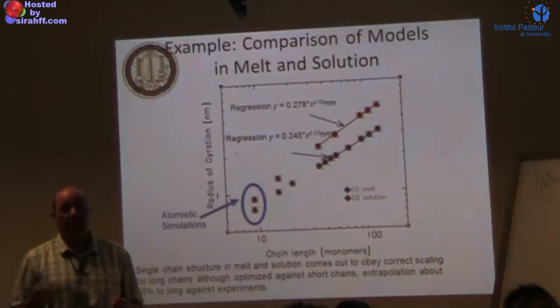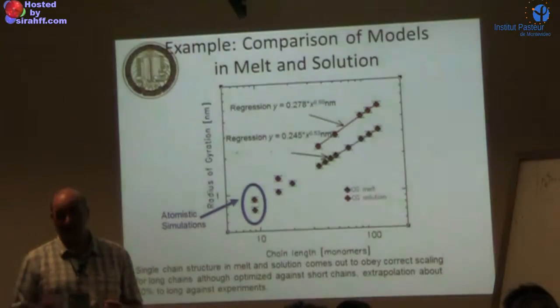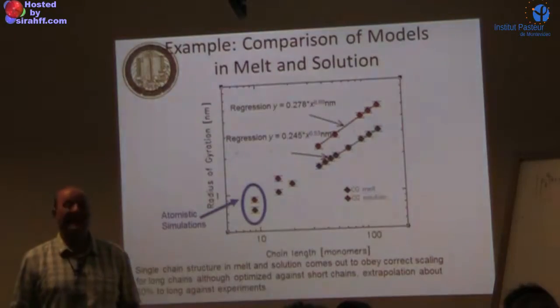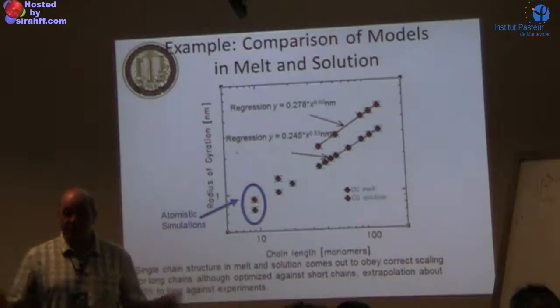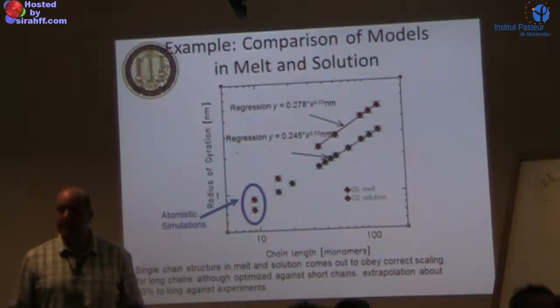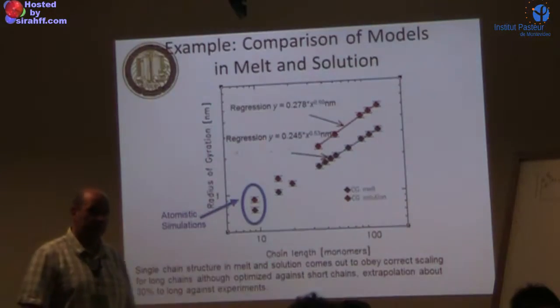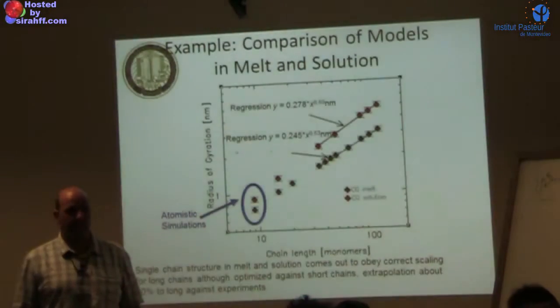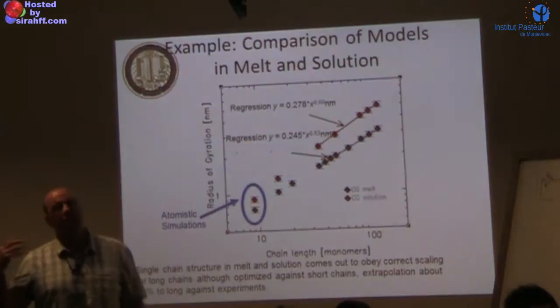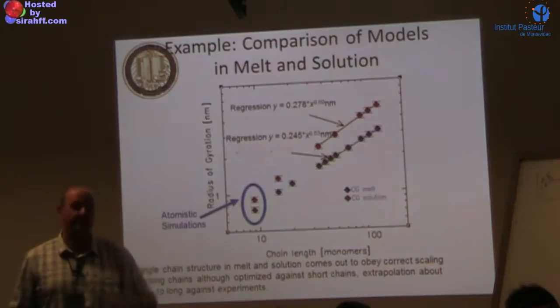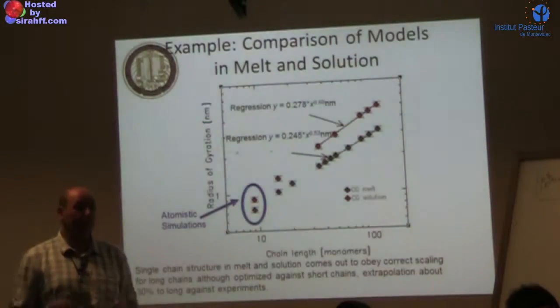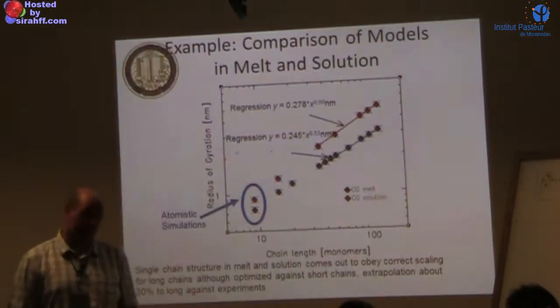This is essentially the major statement of this second talk: if you change your conditions, in almost all cases you have to re-optimize. The exception is if you just change the chain length — making the chain longer or shorter — then you can transfer, and that is the main strength. But everything else — temperature, solution concentration, or deep confinement — makes a difference.